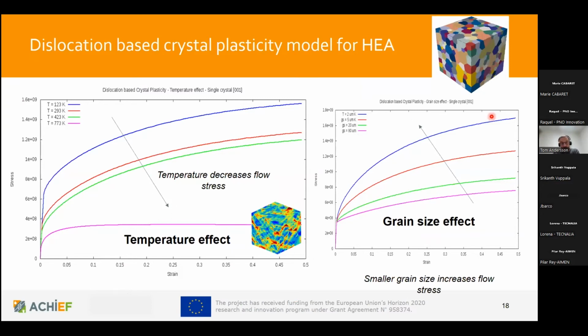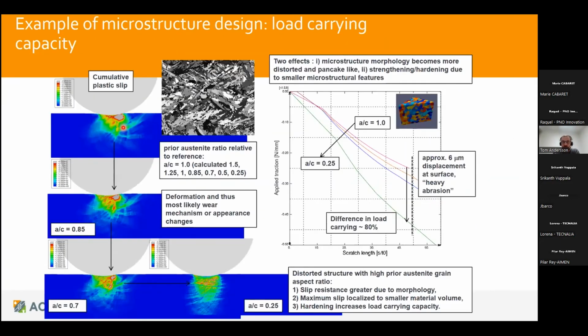And here's an example of how these different parameters affect our temperature and grain size effect. In this case, this kind of single crystal model is computed to see, for example, what kind of effect temperature might have, and also the grain size. And also one example, so basically when we have the material calibrated, we have done a bit similar analysis before. In this case, we played with the aspect ratio of those prior austenite grains, so basically how elongated they are or how round in principle they are, and how that affects the load carrying capacity of the material. So this similar kind of analysis will be done for this in the future also.